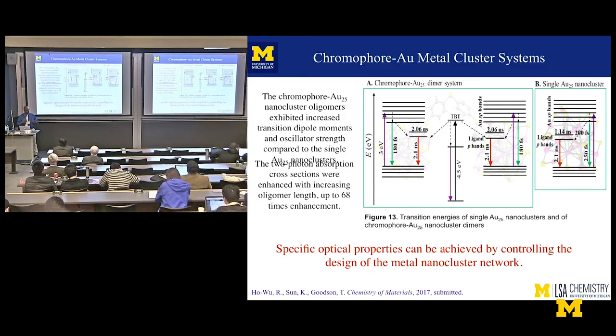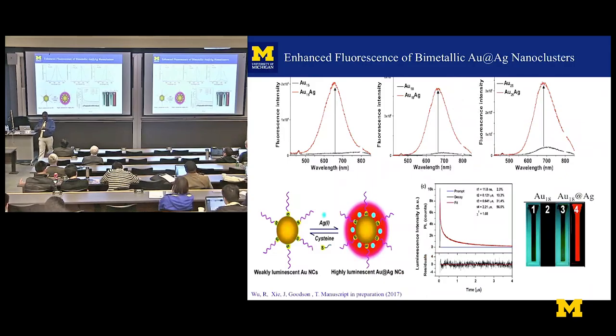So I've shown you something about gold metal clusters and their size dependence, and that they're different from particles. Silver has almost the same electronic structure but has different properties that you can tailor. And now you can make a topology with a gold cluster and a dye and change the properties also. A fellow in Singapore said, what if I could make a cluster with two different metals? Is it possible to make a magic number with two different metals? And he did. You can make the gold 25 silver, the gold 18 silver, or the gold 15 silver. As long as it follows that formula, it's a magic number.